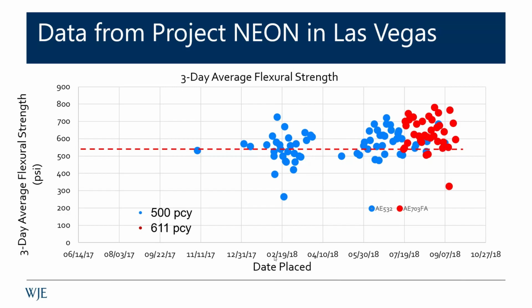You can see the 3-day flex strengths here. But we were starting, because it was July in Vegas, the heat was starting to get to us. We were starting to have some workability issues, mainly due to water control. And so they switched to the 611 pounds per cubic yard, the red dots. And you can see almost effectively no difference in strength. Maybe you could argue slightly higher on this 3-day, but take into account the higher temperatures.